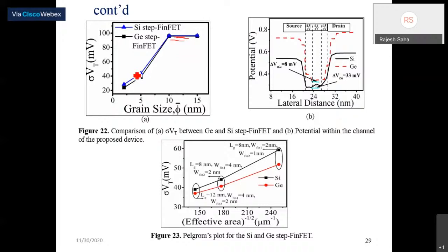In order to examine this result, we have to see why it happens, because germanium has a higher dielectric constant. Due to the higher dielectric constant, it shows better performance in terms of variability compared to silicon. Again, in order to examine this result, we have plotted the potential plot.